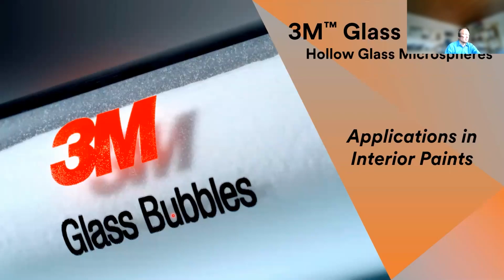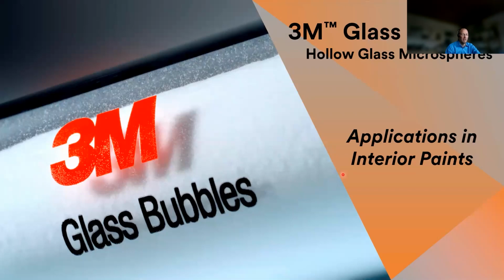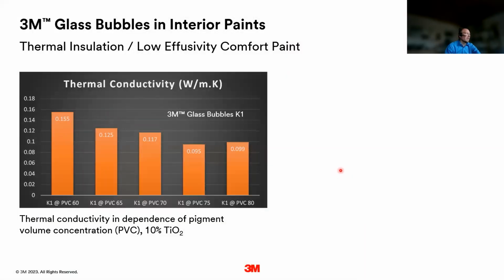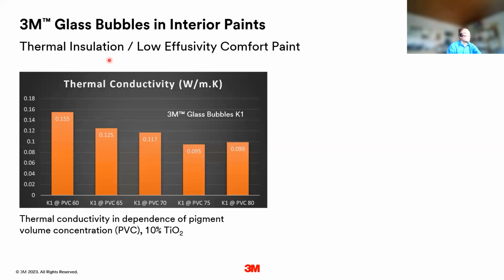So with that, I want to step inside and talk a little bit about applications for interior paints and the benefits glass bubbles can bring in this application. So here we find bubbles in products that are marketed for thermal insulation or low effusivity comfort paints. I'm talking about that in a minute, what that actually is. Thermal insulation, I think that's pretty clear. We see here that if we formulate paints with higher contents of glass bubbles, so you see here also the PVC is increasing, we can get very, very low thermal conductivities for paint, down to about 0.1 watt per meter Kelvin.